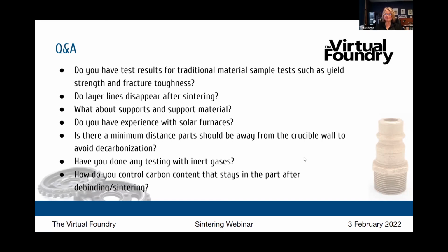Now, this next question was directed at Matthew. Talk to us about the minimum distance that the part should be away from the crucible wall to avoid decarbonization. I don't know if there's just a minimum distance for decarbonization. I know you might want to put a minimum distance away just so that the effect of the heat coming in from the sides doesn't affect the shrinkage. I found that when you have it in the center, the heat comes in from all sides, and then you get it uniformly hitting each side at the same time. But if you have it close to the wall, you've got heat coming in from the wall, but towards the center it's going to be cooler because the heat hasn't gotten there yet.